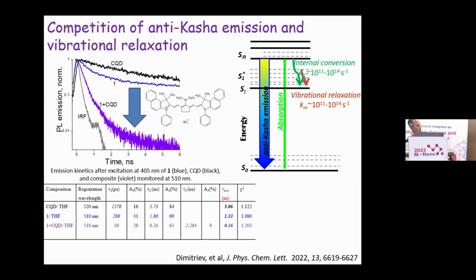And indeed, we observed the kinetics of photoluminescence of these dyes. You can see the kinetics change significantly. That means that the rate of relaxation of anti-Kasha emission increases significantly. Here you can see the numbers in terms of the time constant. For example, the dye alone has a time constant of emission of approximately 5 nanoseconds, but in the presence of nanoparticles, this time decreases by a factor of 4.